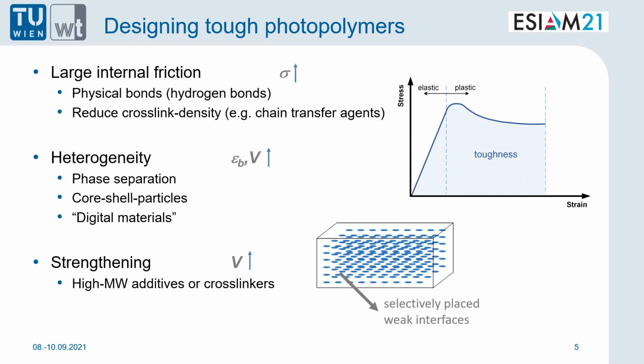Historically, we have been working with stereolithography-based printing systems in our group at TU Wien because they have many advantages. Most of all, a very high resolution when using laser-based systems, but also with certain projectors. The surface quality is really good, actually unparalleled, and when using DLP light engines, printing can be really fast. But however large their advantages might be, material properties, throughput, and the lack of multi-material printing were ever a point of discussion.